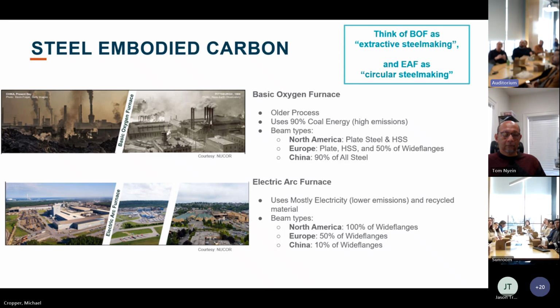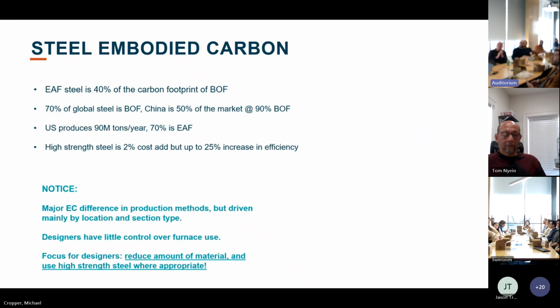And the reason that's important is because electric arc furnace is much more efficient. They're using a higher percentage of recycled content. So the embodied carbon of electric arc furnace steel is drastically lower, about 40% of the carbon footprint of basic oxygen furnace steel. There are a lot of numbers on this screen, but I do want to cover most of them.